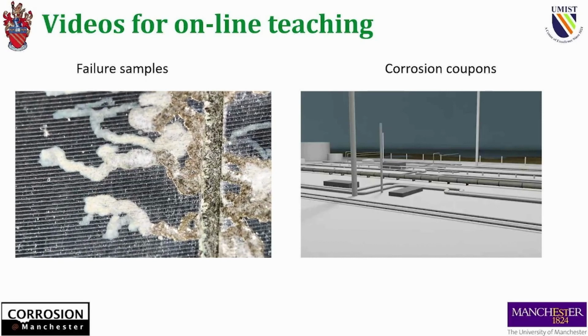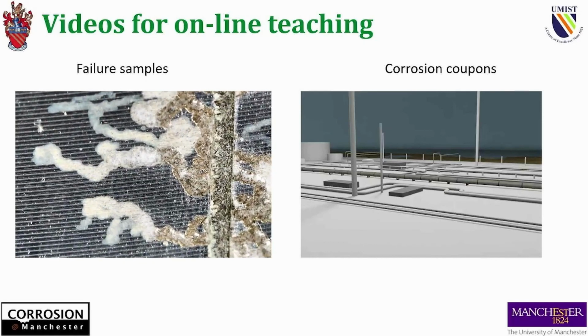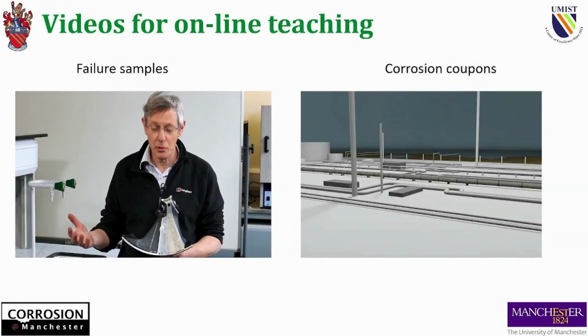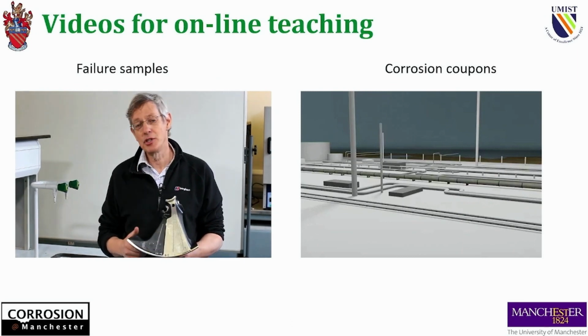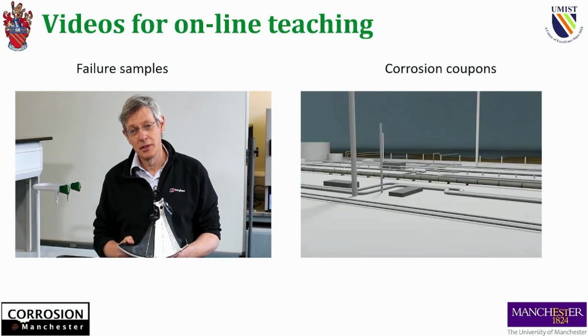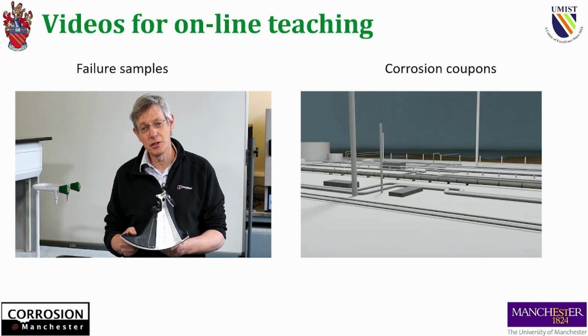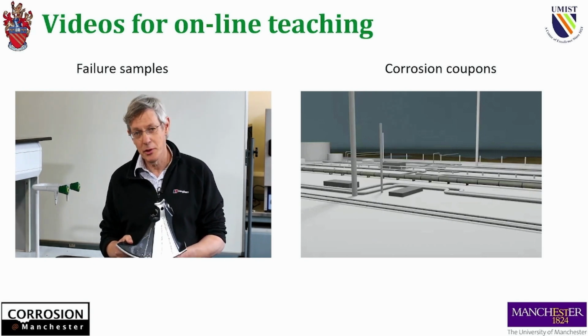It is, of course, not damaging to the mechanical properties of the wheel. The wheel is perfectly okay, but it is damaging to the aesthetics of the wheel. So this is an example of corrosion that does not cause mechanical damage, but causes aesthetic damage. So we've got about 15 of these videos showing some of the corrosion samples that we have in our corrosion museum, and we're going to do some more.